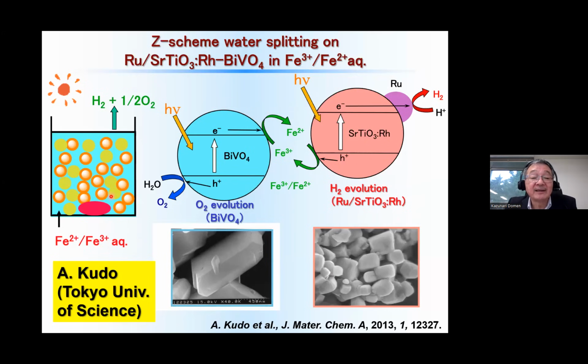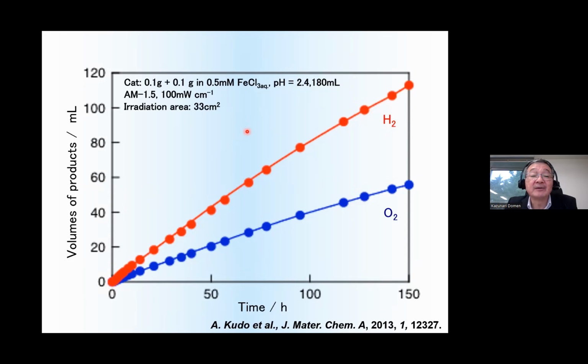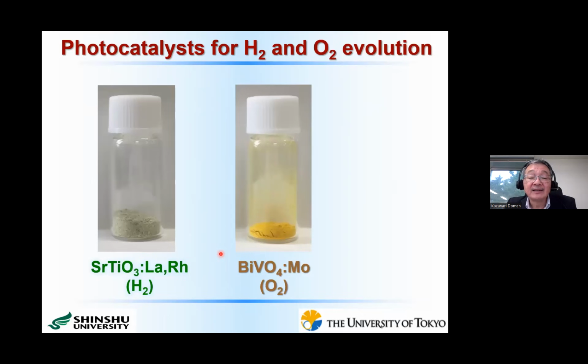Then, after optimizing the reaction conditions, they carried out a water splitting reaction using a solar simulator. In this case, for about 150 hours, both hydrogen and oxygen evolution took place exactly in a 2:1 ratio with almost stable activity. At the beginning of this reaction, the quantum yield at 420 nanometers was about 4.2%. This is a typical quantum efficiency in a suspended, aqueous system using the two-step overall water splitting reaction. Then we decided to utilize this kind of system to construct our photocatalyst sheet.